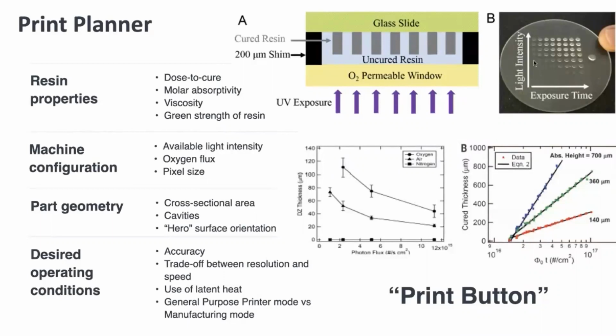The other thing we need to control is how far the light will penetrate into the resin. We control that by controlling the optical density of the resin at this wavelength using dyes, and really tighten up the volume fraction, the voxel, if you will, between the X, Y, and the Z axis using oxygen, understanding the oxygen concentration, the light using dyes to control the light, and the physics of the XY pixel size. And so with that, you can imagine that every resin's different. Its molar absorptivity is different, its reactivity is different. The green strength of the part, there's lots of forces on the part if you have overhangs and the like, and so we've got to be careful to control that.